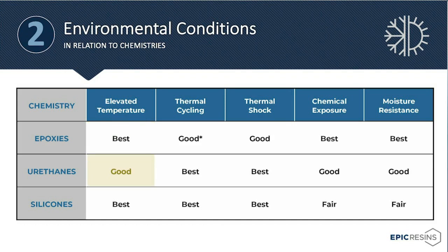Urethanes can have good elevated temperature resistance, not quite as good as epoxies, again, because we can't attain as high a cross-link density as we can with epoxies. Silicones are also in the realm of epoxies in the fact that they have a different chemical backbone, which allows silicones to have good temperature resistance as well.